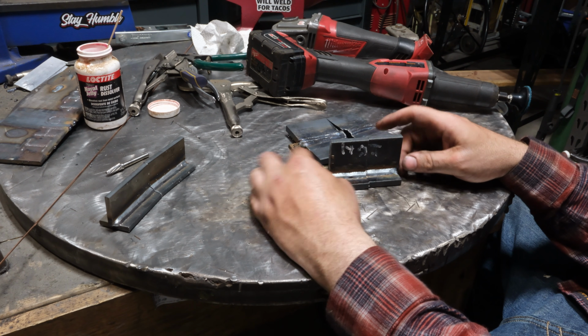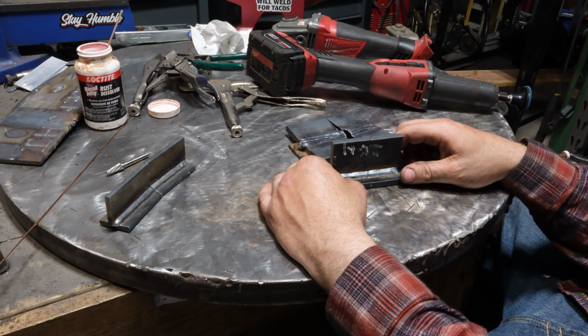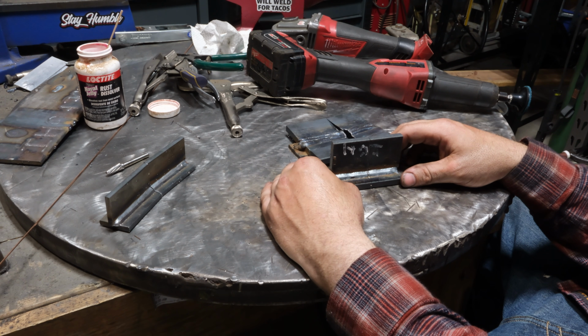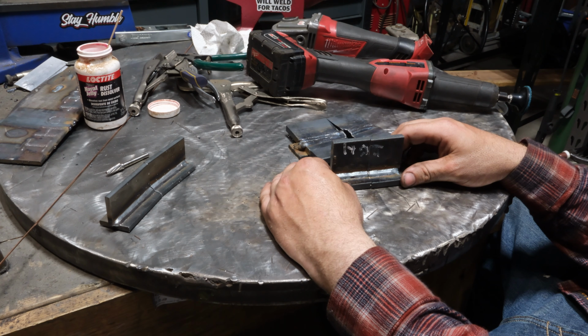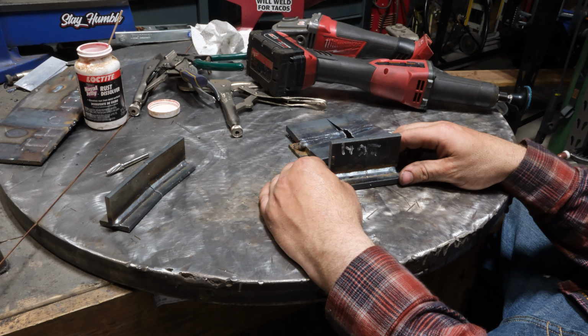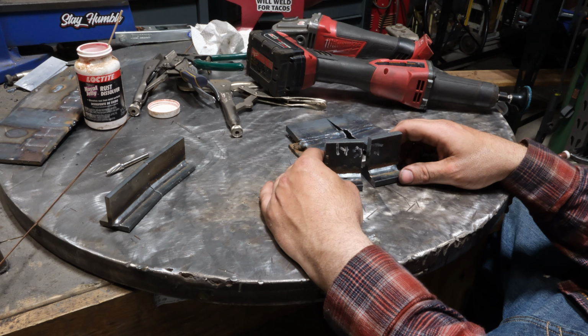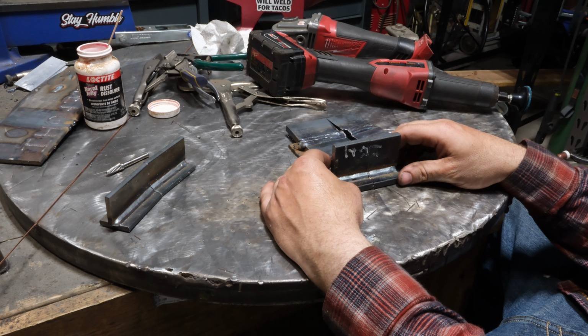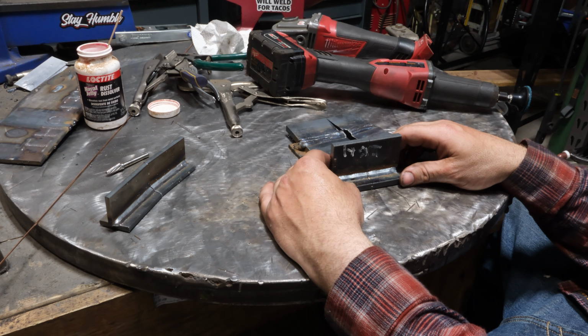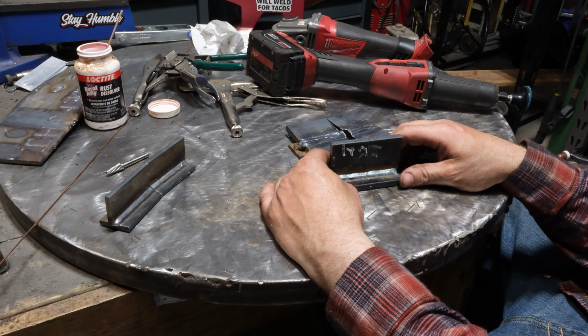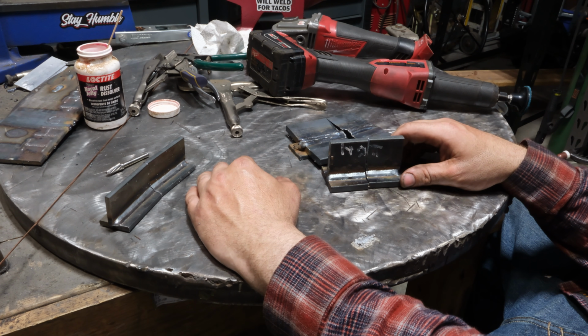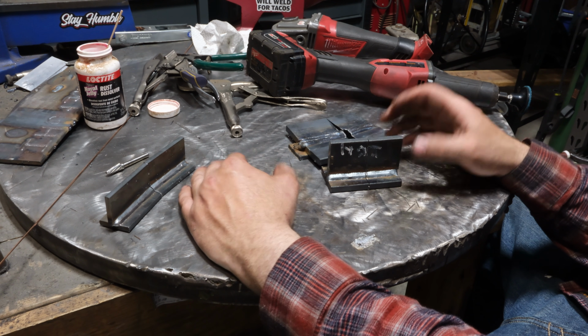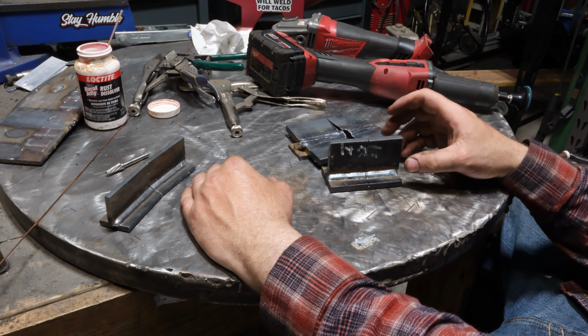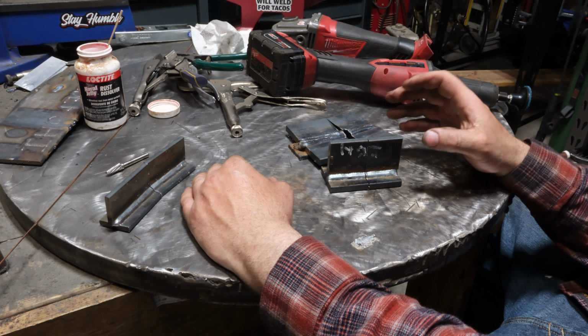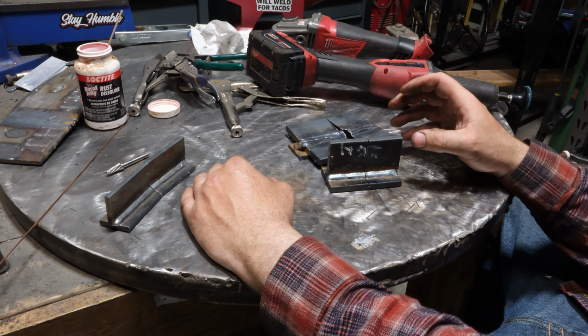Now, the higher, hotter settings definitely overall were better. Keep in mind that those settings were probably in the ballpark of 220 amps. I mean, when you start talking 470 inches a minute and 23 volts, you're up there. It almost doesn't sound like short circuit anymore. And the performance is there on 3/8. But again, I wouldn't necessarily want to make a habit out of it on 3/8, and definitely not on anything thicker than 3/8, simply because of the issues that you have where if it isn't perfectly surface prepped, etc., you might run into issues. But is it capable of a fillet weld on 3/8? Yes, it is.